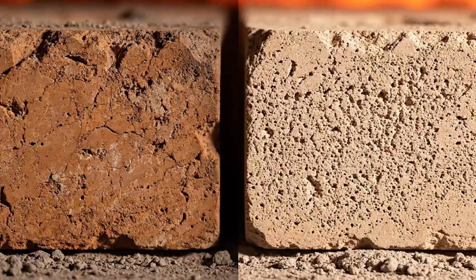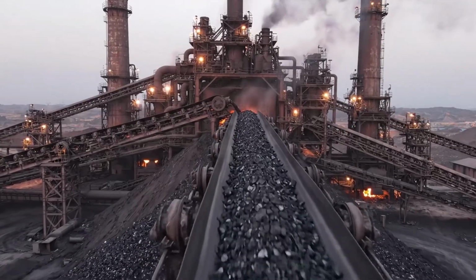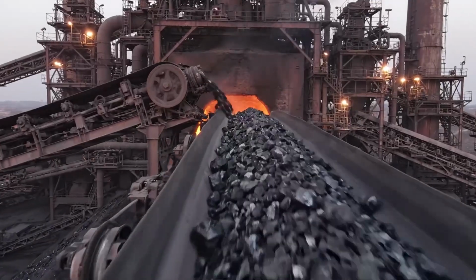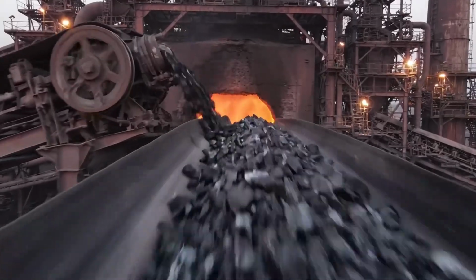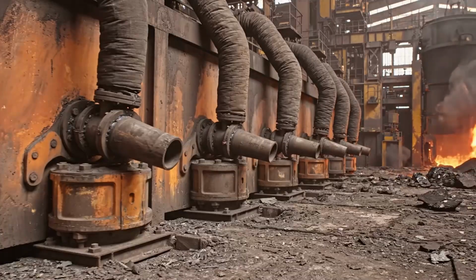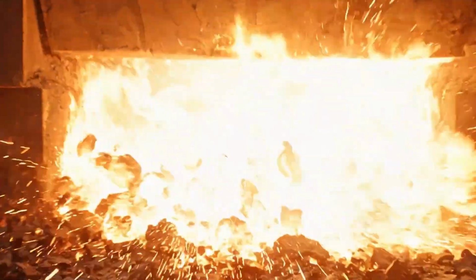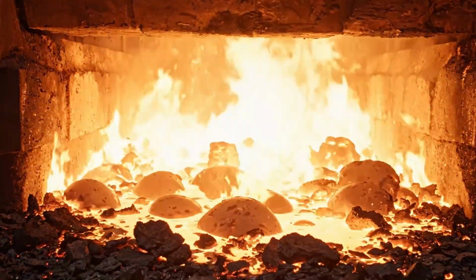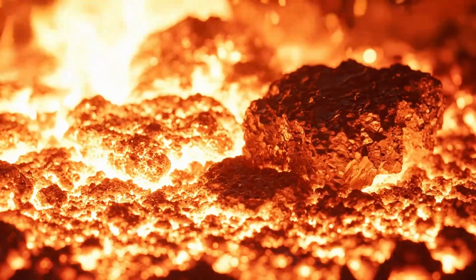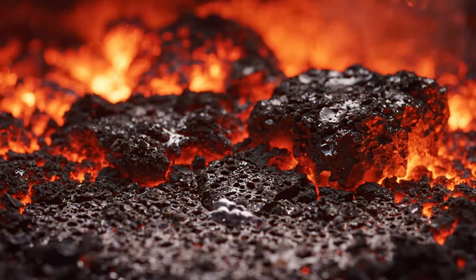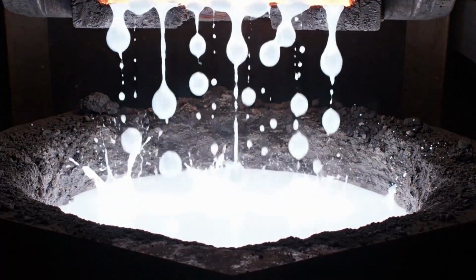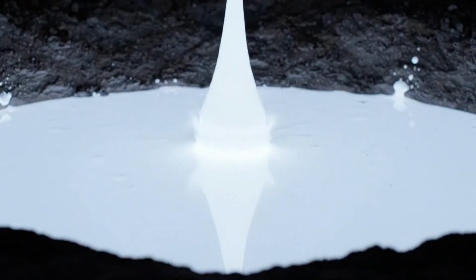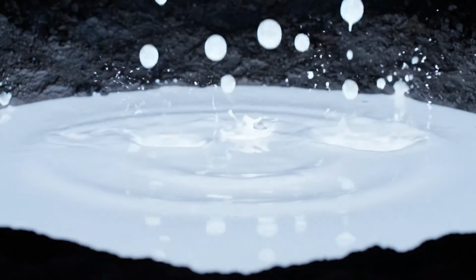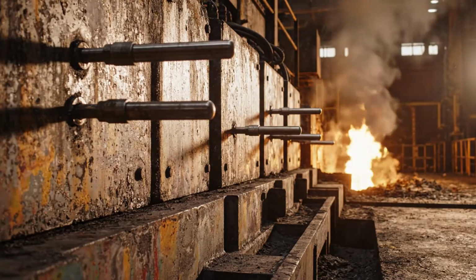When optimal conditions are reached, the operator opens the tap hole, an opening sealed with refractory clay that yields to a precise blow of a sledgehammer. What emerges is a blindingly bright jet of liquid lead that flows through the cast iron channels like sunlight condensed into metal. The slag, lighter than lead, floats on top and is separated by overflow into side channels, where it solidifies into black, porous blocks that will be processed later to recover the trace metals they contain. The primary lead, still impure but already unmistakably metallic, falls into the receiving kettle with a dull, heavy sound that makes the plant floor vibrate.